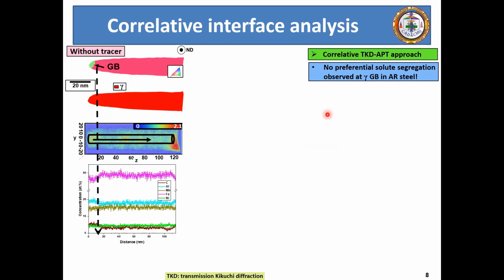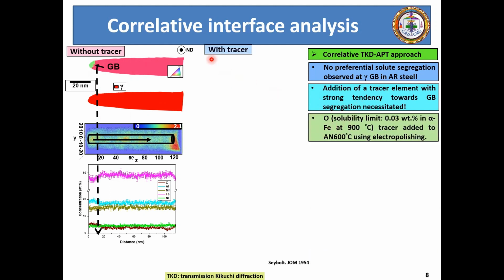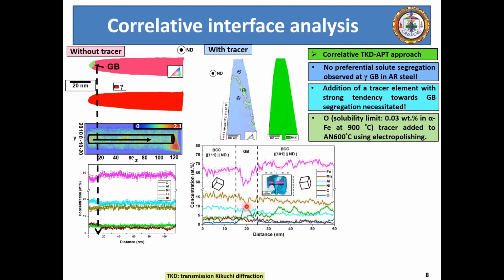And similarly, this means that we have to now add a tracer element which should have a strong tendency towards undergoing grain boundary segregation. So when we now perform the similar experiment with tracer addition, where we have used oxygen as a tracer with a low solubility limit in alpha iron even at an elevated temperature, we can clearly observe a segregation of oxygen at a BCC grain boundary.